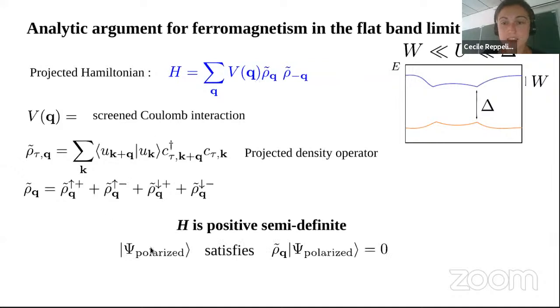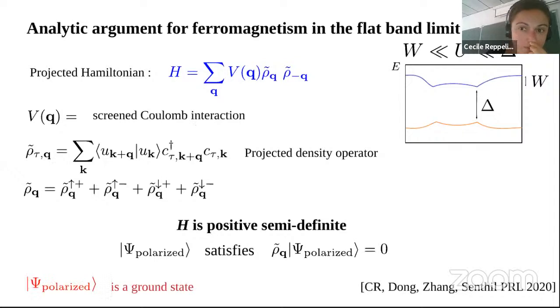The second argument is that if you take a fully polarized wave function at integer filling, so let's say I'm using filling 3, like in the experiments, then this wave function satisfies rho Q psi polarized equal to 0. If you apply the projected density operator onto it, it'll be 0, which means that psi is an eigenstate of this Hamiltonian with eigenvalue 0. So it has to be a ground state. It doesn't have to be the only ground state, but it is a ground state.